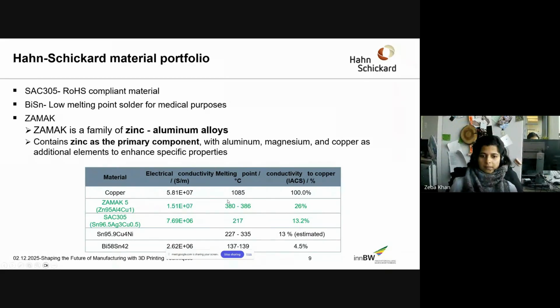And if you see here in this chart, even though there are people who are able to print copper in terms of conductive inks, like I mentioned earlier, it is difficult to sinter it to the temperature that you can get the actual conductivity of the material or the conductance of the material. And that is where we have the advantage, because we are printing bulk metal, and despite this conductivity difference, we're able to achieve the conductance needed for the tracks.